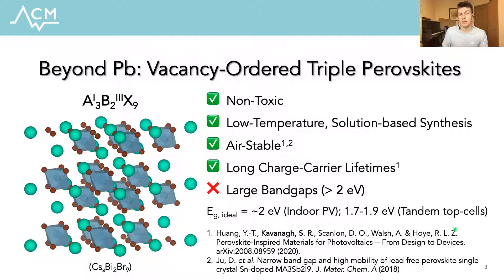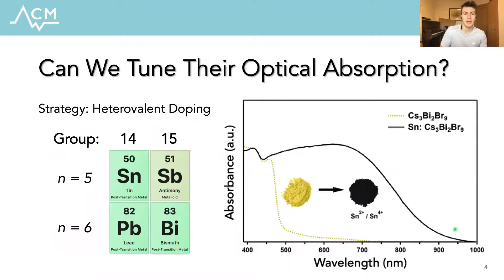Unfortunately, however, these materials exhibit large electronic band gaps which, although suitable for certain optoelectronic applications such as x-ray detectors, prohibit their use in most photovoltaic or photocatalytic devices. As such, the objective of this work was to identify a route to enhancing the absorption of these materials within the visible range so that they may be more suitable for the majority of photo applications.